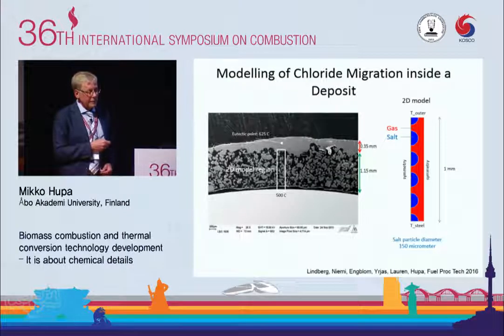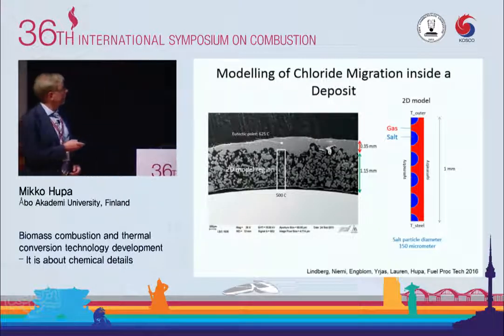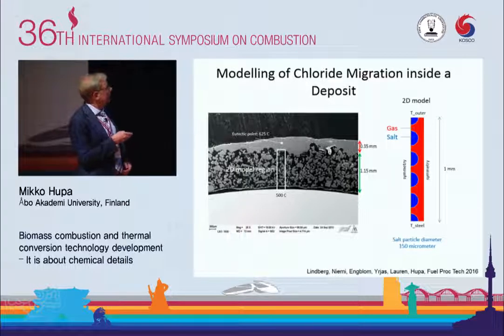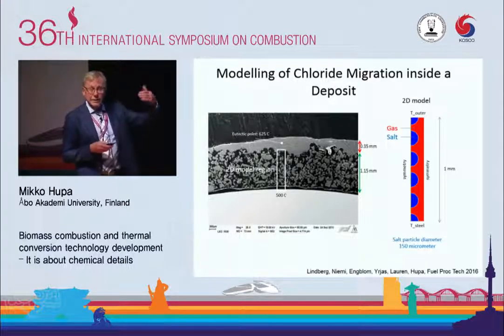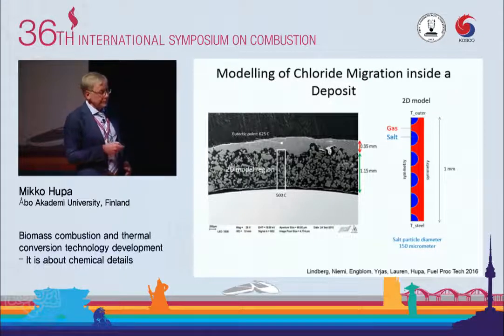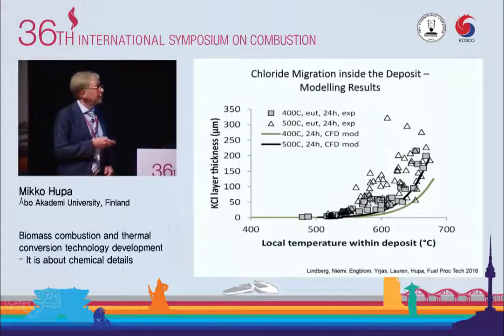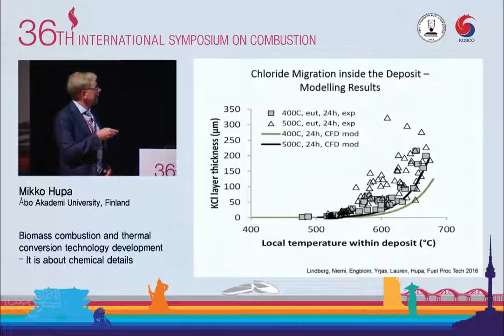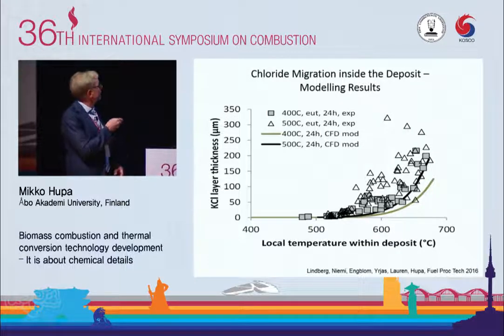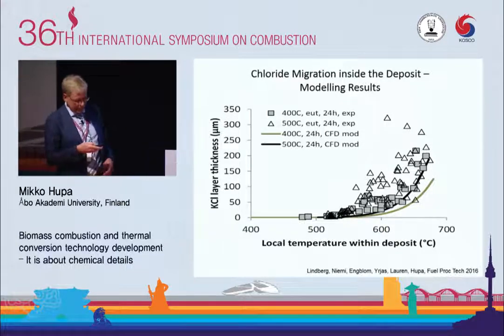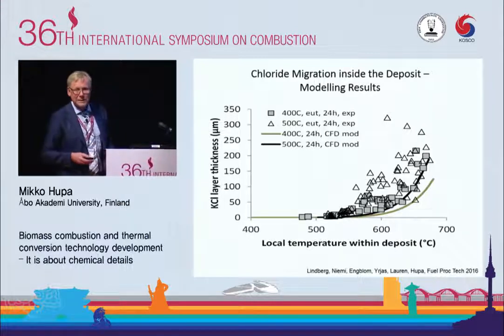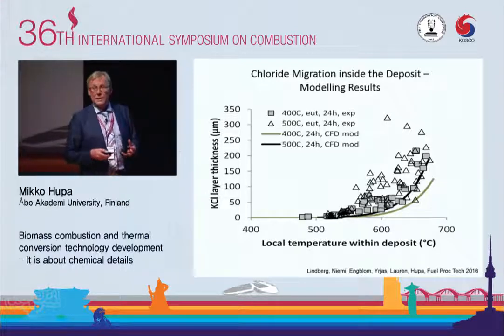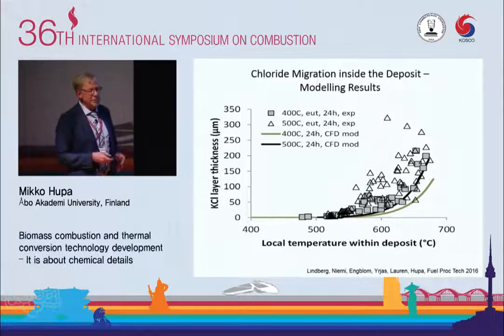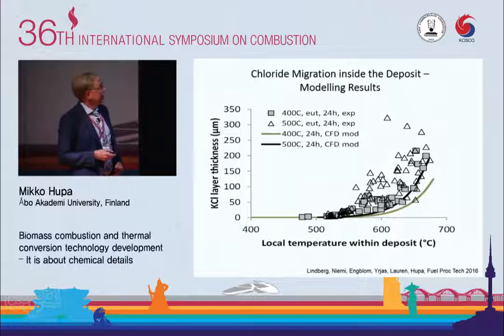We have been able to model this phenomenon by a two-dimensional vaporization condensation model, and we can get some theoretical curves which fit quite well to the layer thickness. We can measure the potassium layer thickness as a function of time. This is a new area. We call it gradient chemistry, inorganic chemistry in temperature gradients. It can be important in other applications as well.